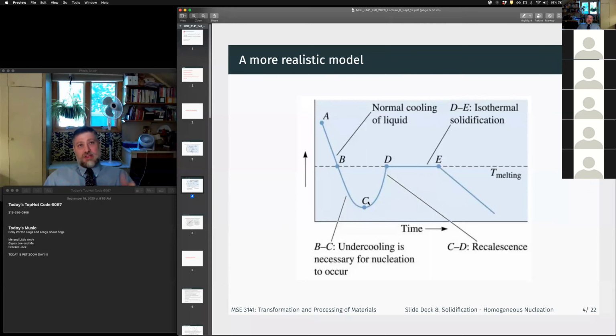Essentially it was in an induction furnace, so everything was able to stay nice and cool. You had red hot liquid, well, white hot liquid, come down through the cooling temperature and actually got an undercooling of about 200 degrees, when all of a sudden it instantaneously froze and the temperature shot back up to the melting temperature when it was completely solid.